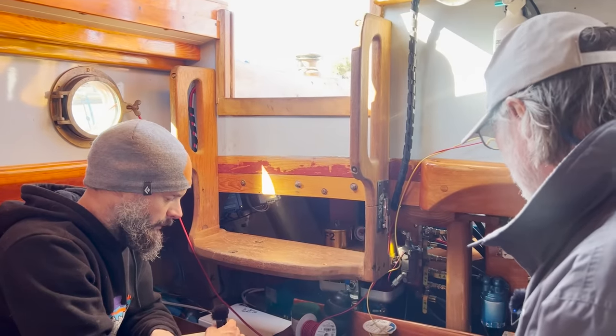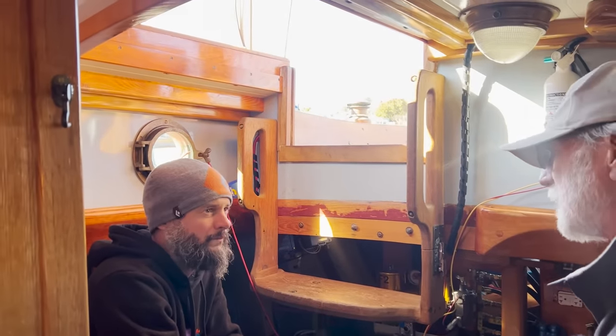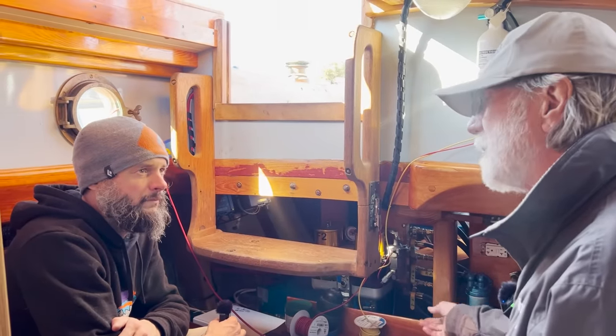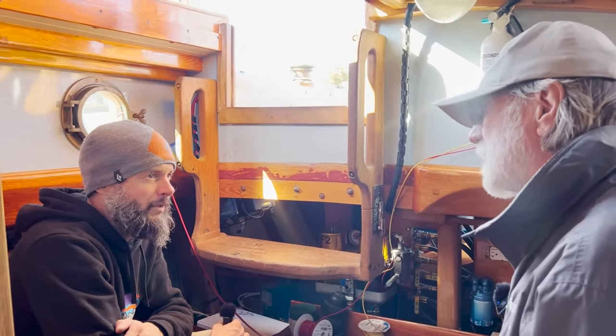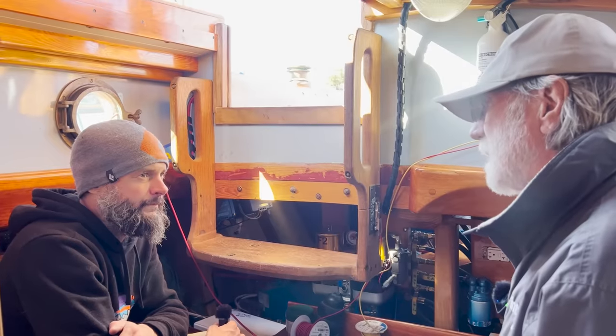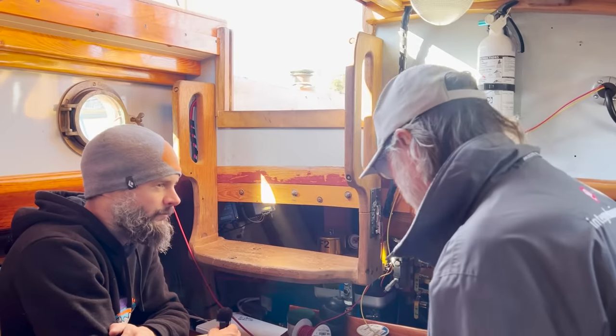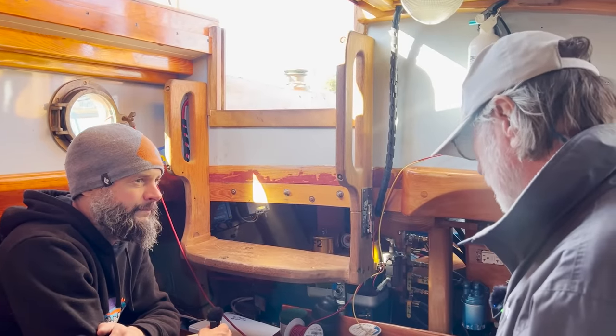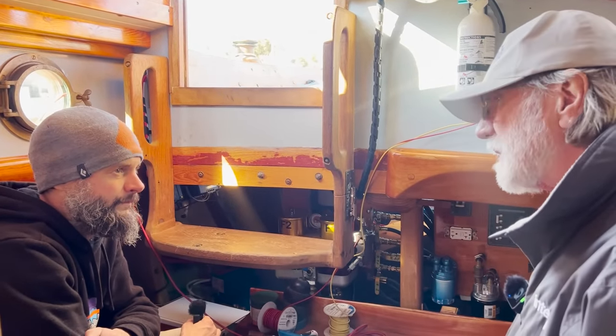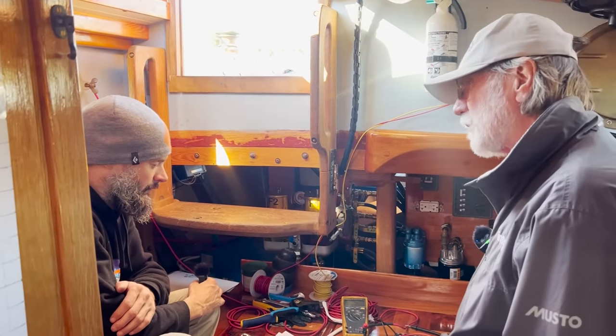We got a shift when you revved up. What did we get up to, Annie? About 100 amps. Yeah, so we got to a pretty high output from the alternator, and the higher it went, the lower the voltage from the zinc. So we're putting some stray current on there that's counteracting, actually flowing the current in the other direction. What I can't figure out in my own head is exactly what the default current path is. But we've definitely got some impact from the alternator on that whole circuit, which shouldn't be there. It shouldn't have any impact on it at all.